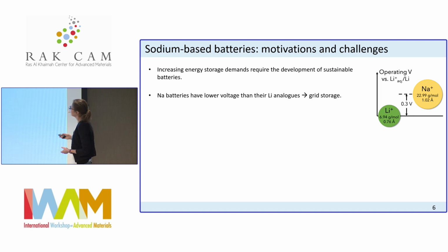Sodium lies above lithium in terms of the redox potential by 0.3 volts, and so this means that the redox potential of sodium batteries will be lowered by about 0.3 volts. So we have typically lower voltage cells with sodium. And it's a little bit heavier than lithium as well. So what this means is that the sodium batteries have a lower energy density, at least by 30% compared to lithium. And so we need to find applications where energy density is less of an importance, and one of them is grid storage.